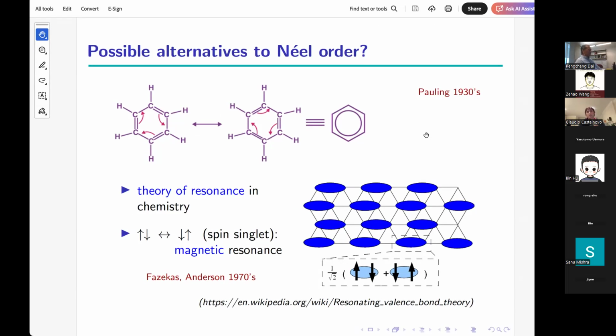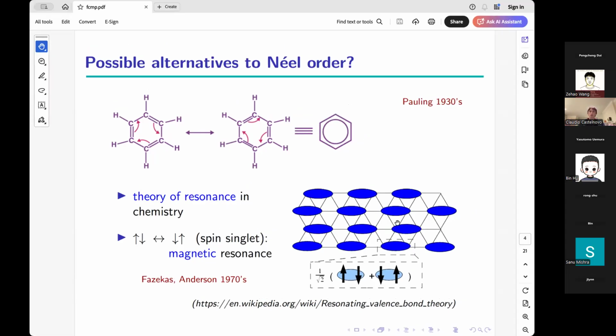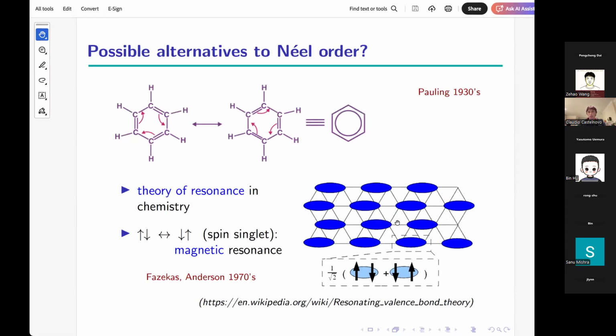I think it depends on the state we have. This here is what would be referred to as a valence bond crystal. It's a regular pattern of these singlets. Generally speaking, if you're asking what would break the massive entanglement, if you have a degenerate superposition of these, you would need something that percolates across. So for the triangular lattice, the percolation limit is probably about 50%. If you break 50% of the bonds, it would still be... I don't remember what it is for the triangular, the square lattice is 50%. But you wouldn't, it should be robust to a fair amount of impurities in general expectation terms.